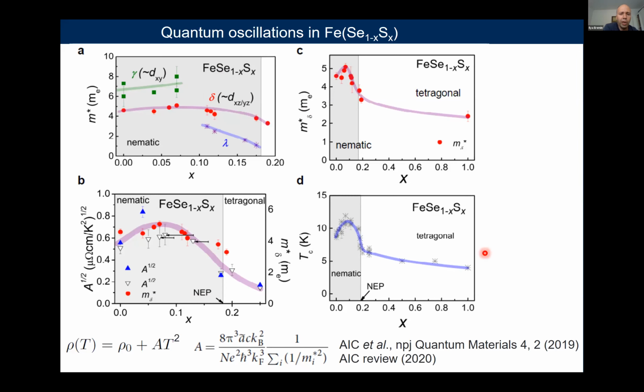If I may still ask, because I see that I can unmute myself, Amalia: does it mean that if you don't see it in the ARPES, you claim that you actually see this gamma band, this outer electron pocket, in the quantum oscillation? Based on the effective mass of this band, which is about 7, we think that's how we assign this particular pocket to the dxy band. Okay, based on its mass, because it's much heavier than the other one.